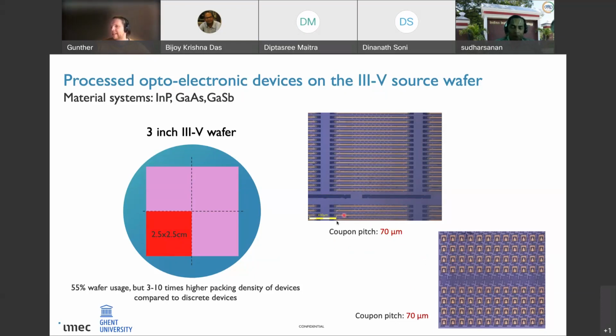So this means that even though you only use 55% of the wafer, your packing density of components is larger by a factor of between 3 in the case of an elongated device, and up to 10 in the case of a square device, such that you make more efficient use of the III-V source material.